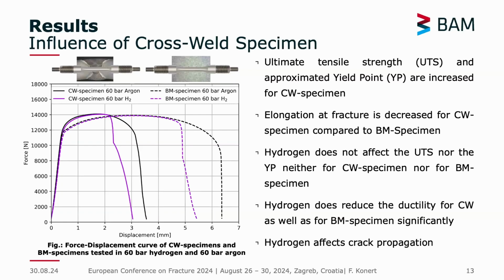have already a quite slight increase in strength, where you see more or less yielding in the force displacement curve, but you have a similar qualitative effect when it comes to hydrogen. So you have also a clear decrease in the elongation at fracture, both for the specimen in base metal, as well as for the cross-weld specimen.